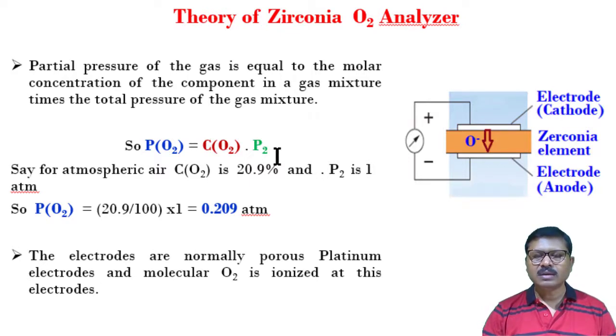Now if we consider one example, then we may calculate the partial pressure of oxygen. Say the total pressure is 1 atmosphere, normal atmospheric pressure, and the concentration of oxygen in normal air is 20.9%, because in this case on one side of this zirconia cell normal air is used and on the other side is the sample gas whose oxygen concentration is to be measured. So the concentration of oxygen is 20.9% and the total pressure is 1. Putting the values here, I will get the partial pressure of oxygen, which is 0.209 atm.